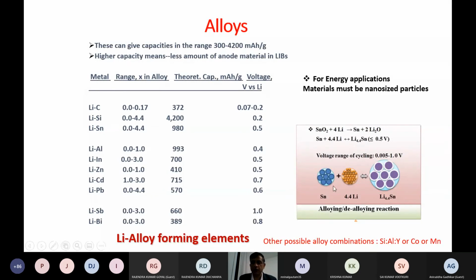And sometimes you can make a composite, for example silicon mixed with aluminum, with what they call spark plasma and different techniques we can do. The beauty of this, although we can prepare it, you remember, it's very important that the material should be nano size. Otherwise, if you have micron size or bigger, it really will not work, whatever way you prepare it. So this is really difficult. So alloys, any metals or oxides, should be nano size materials only.